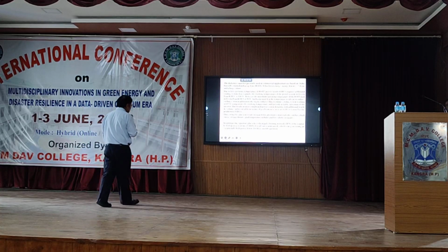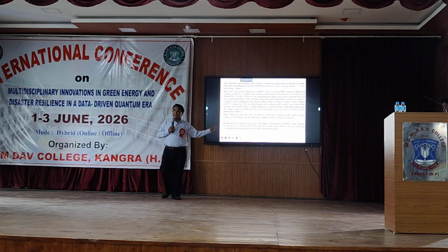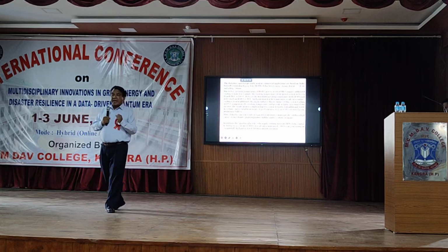So, therefore, the main focus is to search for an alternative material so that it can operate at high temperature. As I have already said, the ferroelectric material can operate up to 250 degrees centigrade efficiently. But the main problem is with that energy storage density.